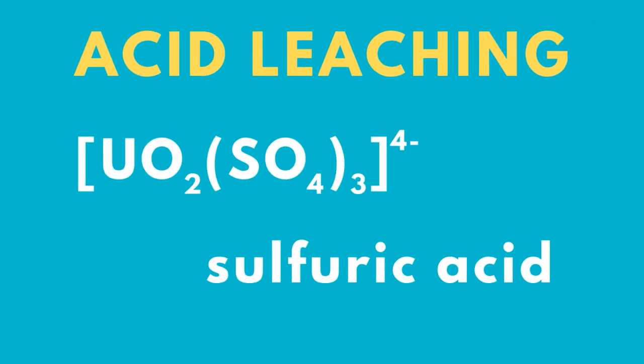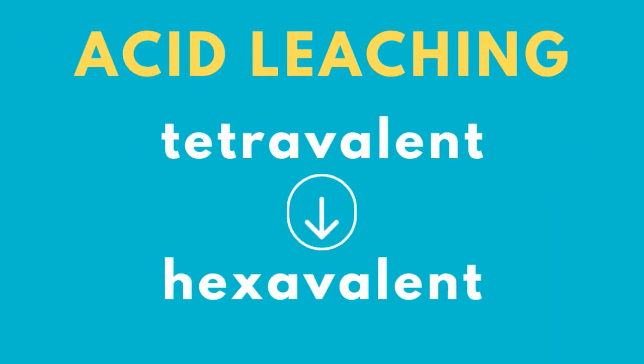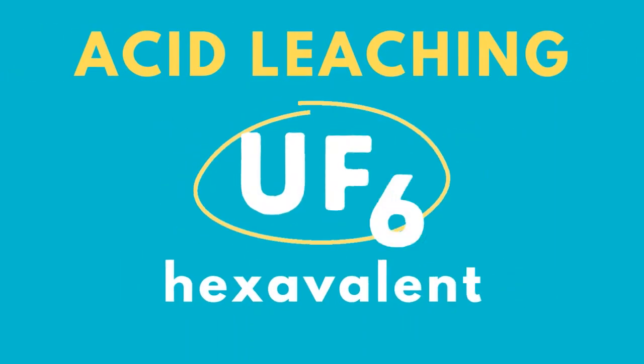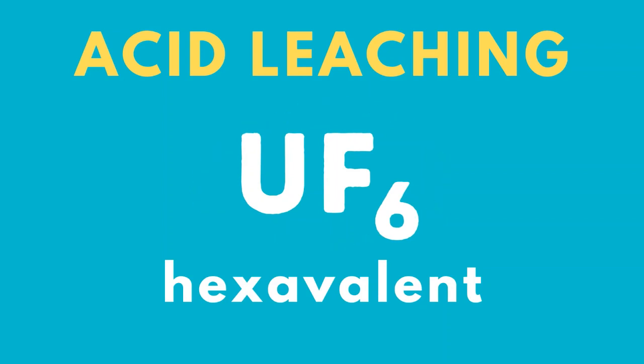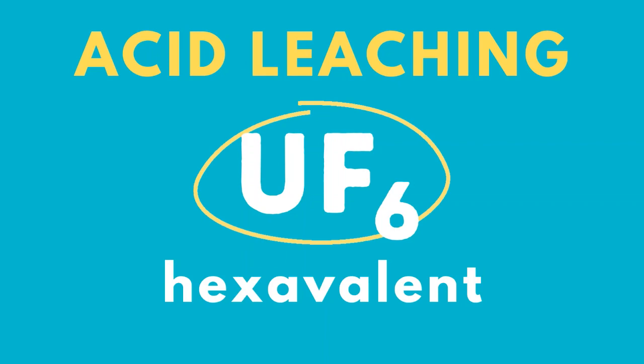This uranyl sulfate complex is highly soluble in sulfuric acid, and so in the leaching stage, the sulfuric acid dissolves the complex and leaves behind the other components of the ore. In the process, the uranium is converted from a tetravalent to a hexavalent state. But why hexavalent? It's because we will be converting our uranium to UF6, a hexavalent gas, in a later stage of our process.